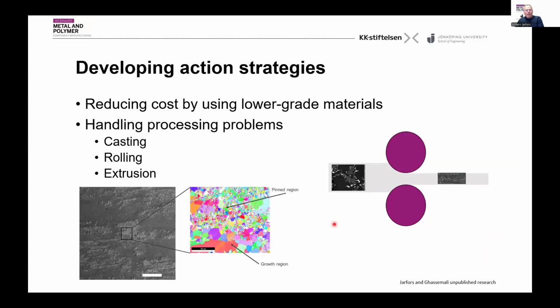Now, when it comes to developing strategies, we need to think about what is happening when you do this. And this is an example from rolling. So we talked about particles. You can see the rolled structure to the left. This is the particle richness. And then you get the microstructures. So what we have is an influence on the homogeneity of the microstructure as a consequence of increased particle content. And then this needs to be rolled or extruded or cast in some way.